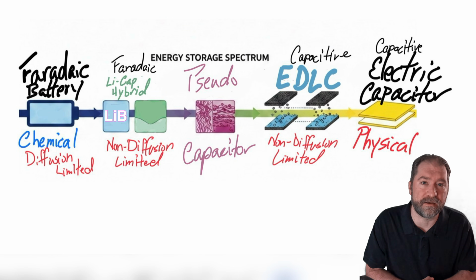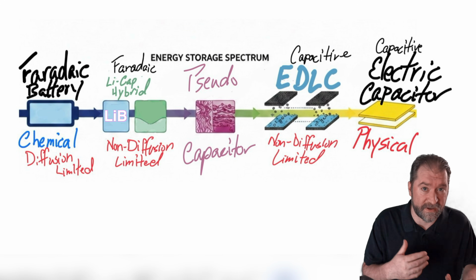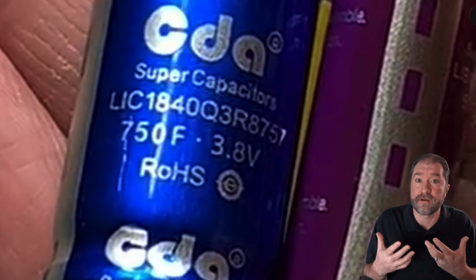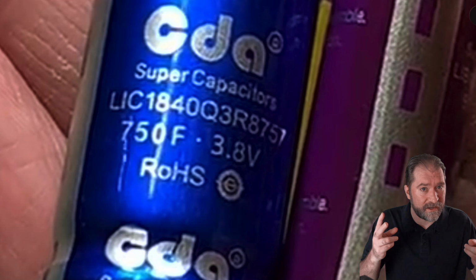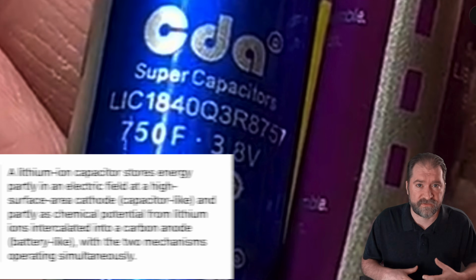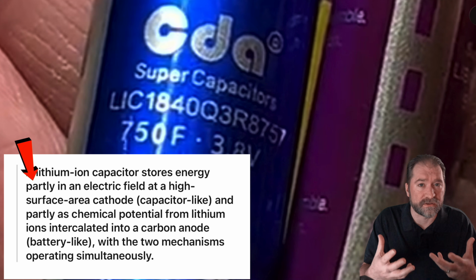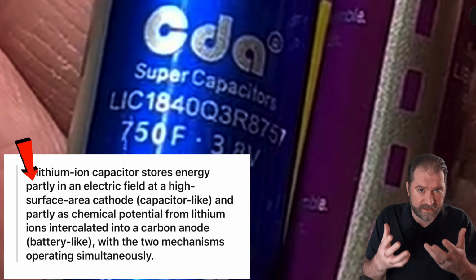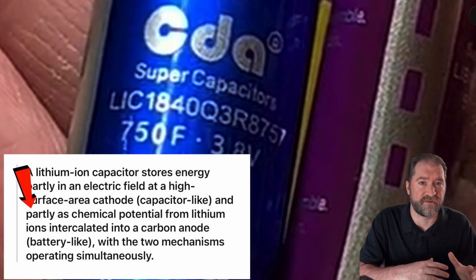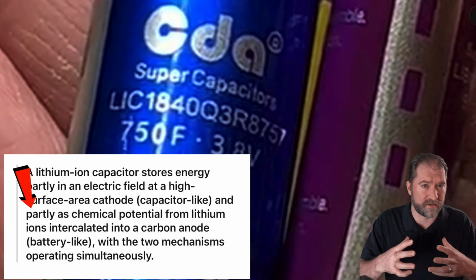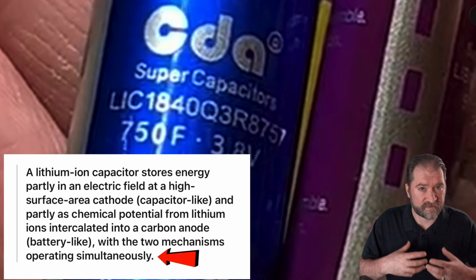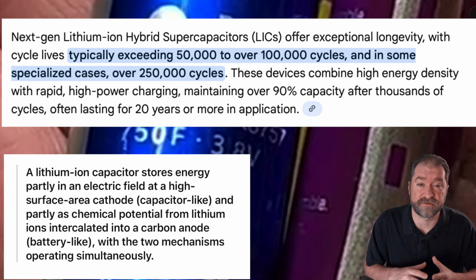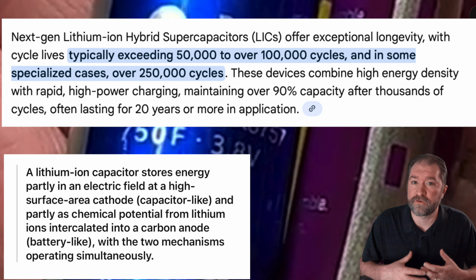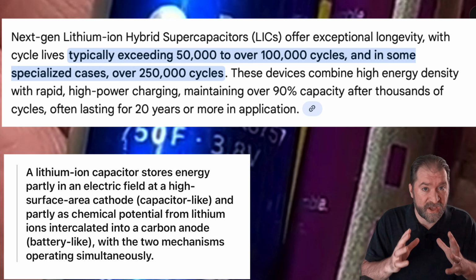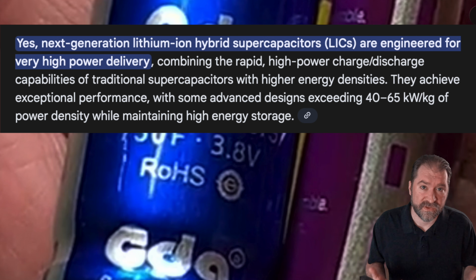We'll talk more about the LIB in just a second, but let's introduce our next candidate on the spectrum, which is also on the battery side, and that's a lithium-ion capacitor. This one is also kind of a hybrid, but it's really just a half and half. You see, a lithium-ion capacitor stores energy partly in an electric field at a high surface area cathode, and partly as chemical potential from lithium ions. And the two mechanisms operate simultaneously. The cycle life on a lithium-ion capacitor is excellent, over 100,000. Charging can take place in just seconds, and the power density, that's the delivery of power, is very high.